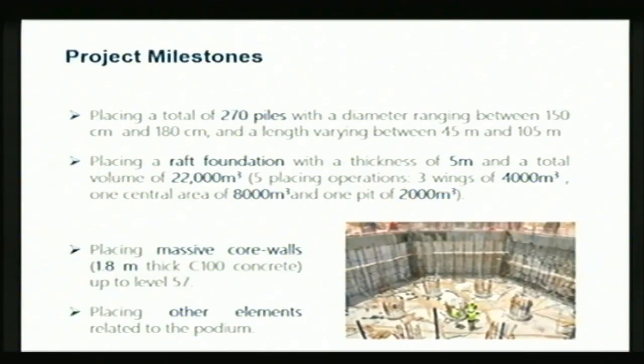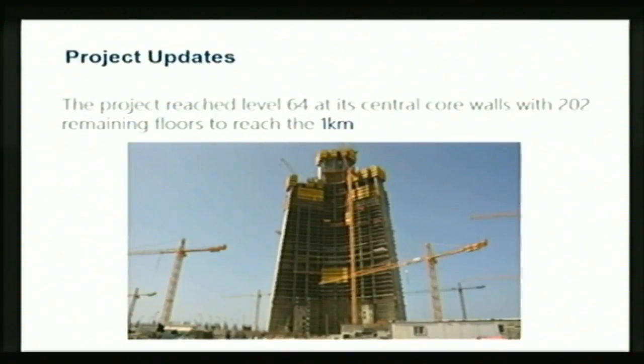Yesterday we heard about mass concrete. This is typical mass concrete. Remember, Jeddah in summer is at least 45 degrees in the shade and 100% relative humidity, and this is what we had to deal with. And the raft foundation happened in August, so that's another challenge that we had to work with. Even the core walls were 1.8 meter thick. You think that mass concrete is mostly raft foundations. It is actually, in this case, even the core wall of the building. And even other elements in the podium and other columns were challenging.